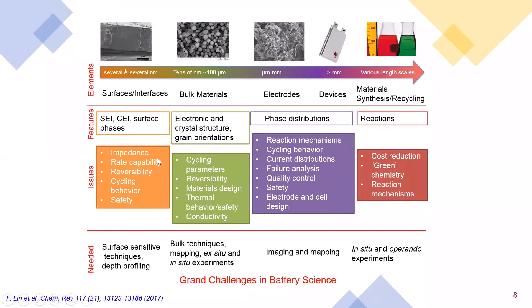These surface interfaces relate to key battery challenges: impedance, rate capability, and reversibility. For these scientific questions, we need synchrotron X-rays that are surface sensitive and can provide depth profiling — for example, XPS, tender XPS, soft X-ray XPS, hard XPS — enabling different depth profiling. You can also use soft X-ray absorption spectroscopy with different detection modes to probe surface information.